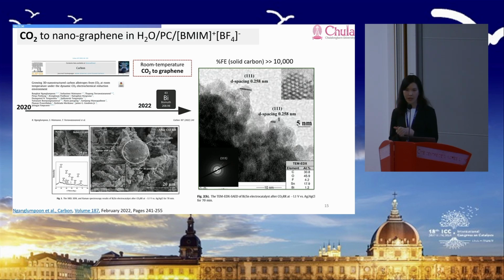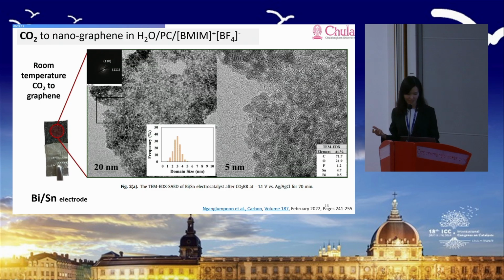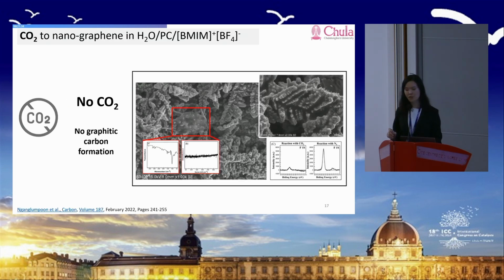And if we calculate the Faraday efficiency, it's way beyond, I put the number 10,000 here, but it's actually way beyond that. So it's not really an electrochemical pathway for the carbon formation. We use a small amount of electricity. The work actually started off with some serendipity, but we are learning a little bit to get to know more about it. This is the graphene that we got from this. It has a size of about 2-3 nanometers, so small graphene pieces are joining together. It's all over our electrodes. That's what we first observed.